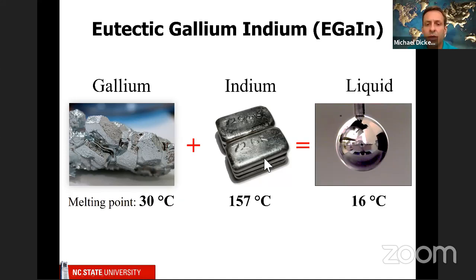But to ensure that it stays as a liquid, we add in other metals. So in this case, using indium, and through one of the magic of nature, you mix these two things together with different melting points, and you get something that's even lower. And we do this by picking the composition with the lowest melting point, which is called the eutectic. So I'll try not to use jargon, but you might see this word e-gain appear in several places, and that just refers to this kind of composition.